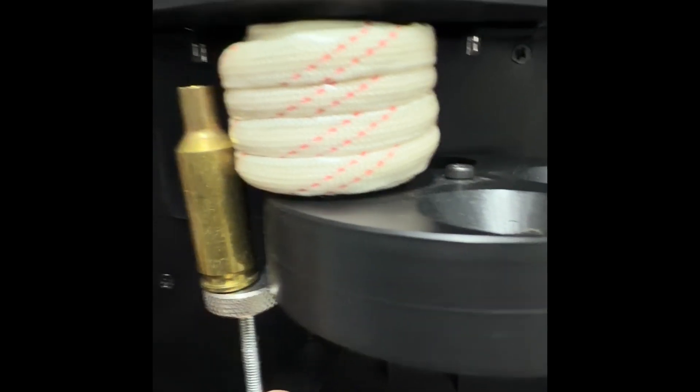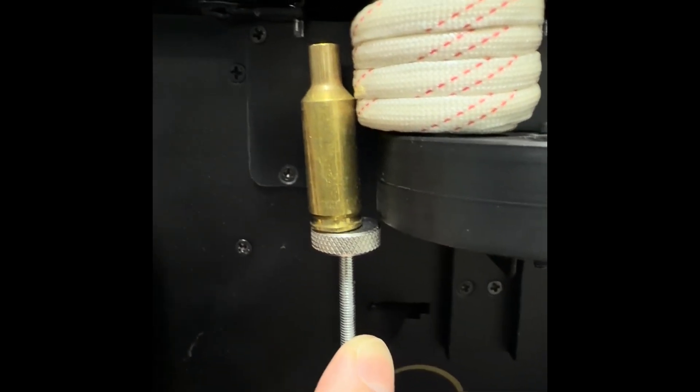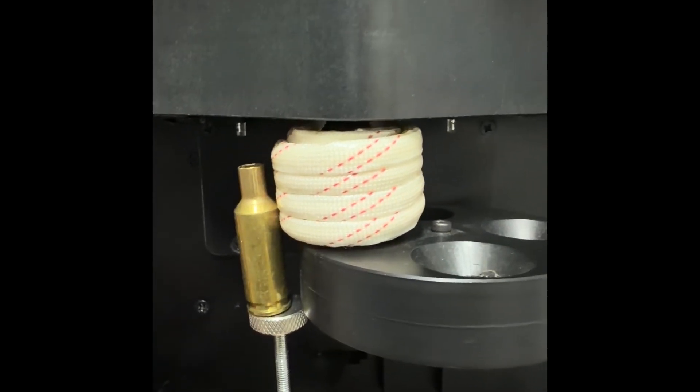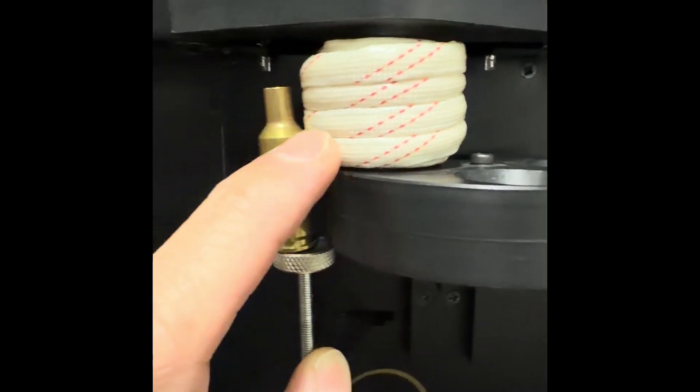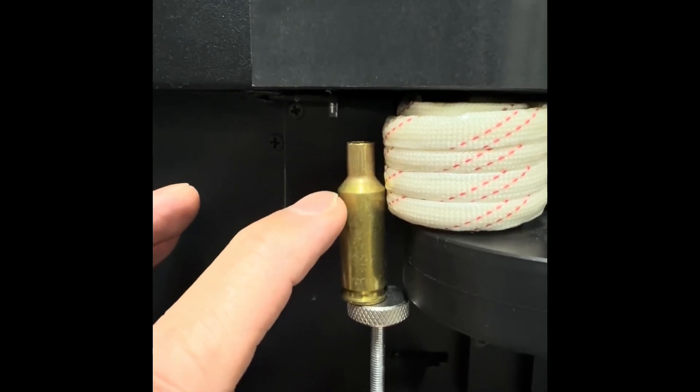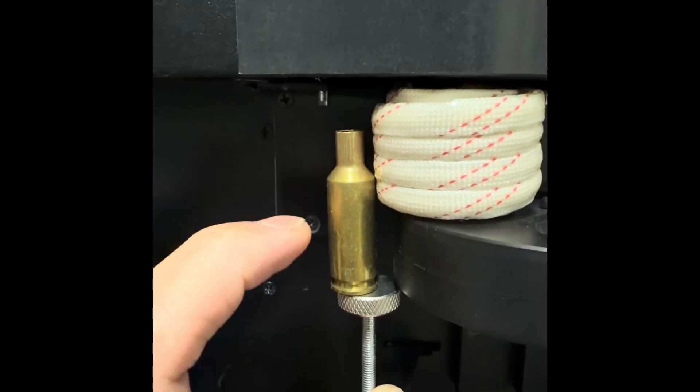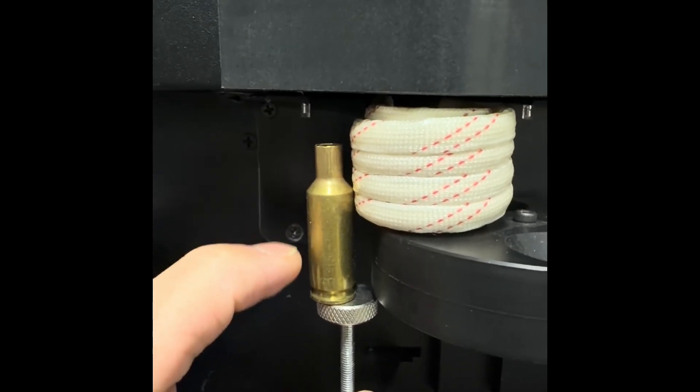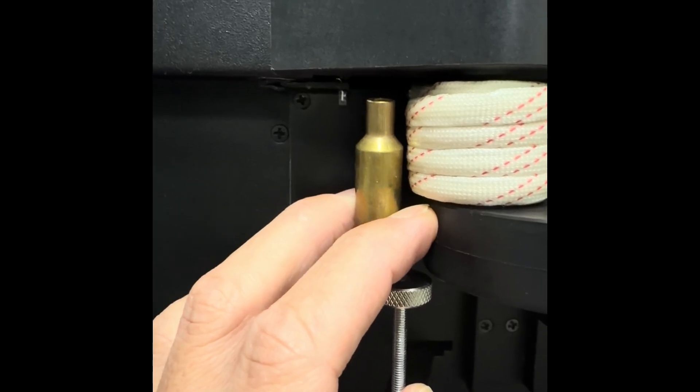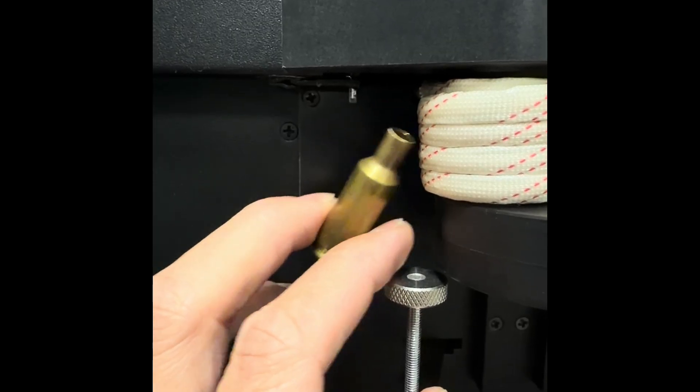Now, if you look at the three coil, the coil on the very top, the first coil, top being number one, the bottom being number four. The heat zone is between the top three coils. The bottom coil produces little to no heat. And ideally, when we anneal, we want to anneal the neck and down to the shoulder. And for shorter cases like this one, 6BR, we obviously have to be cautious for the heat not to migrate to the base. The higher you go, the hotter it gets, right?